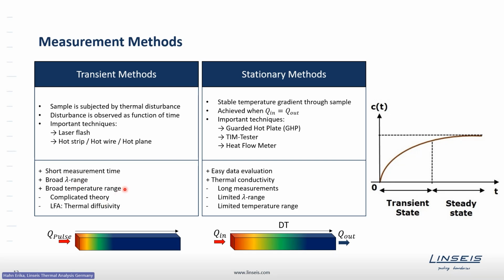Disadvantages in the case of the laser flash, for example, are that only thermal diffusivity is measured and not directly the thermal conductivity. Furthermore, mostly these transient methods have a complicated theory behind them, because you need to model the heat transport within a broad range of materials within a very short time. And this is typically quite complex. Of the transient methods, the most important techniques are the laser flash technique and the hot wire or hot strip, hot plane method, which we will have a look at in a minute.